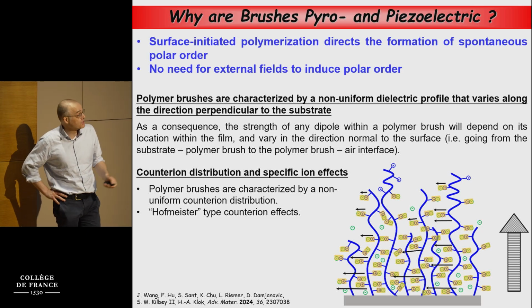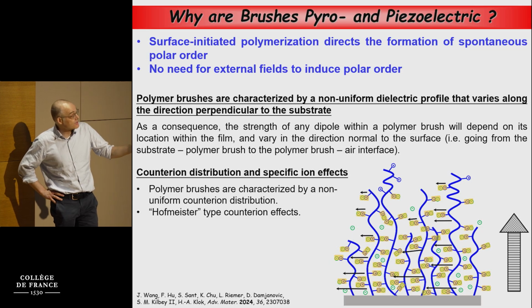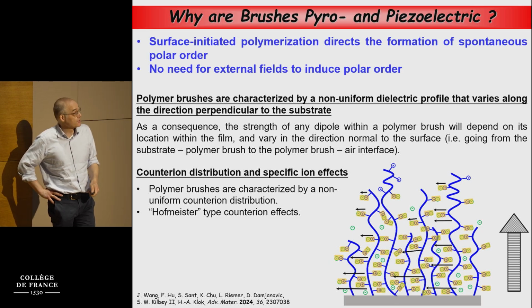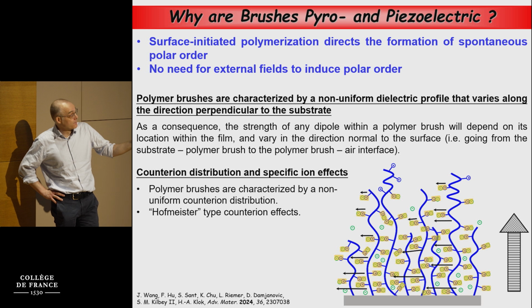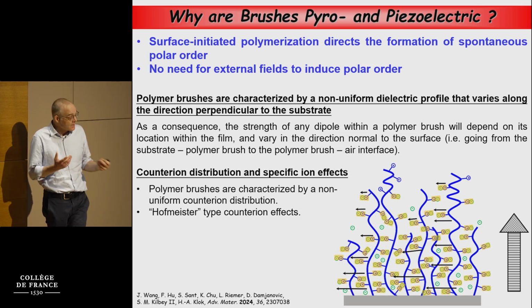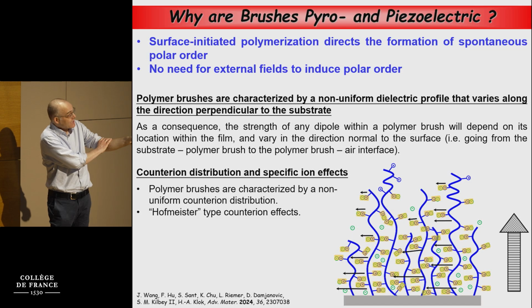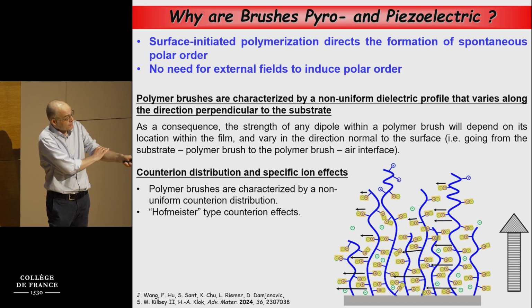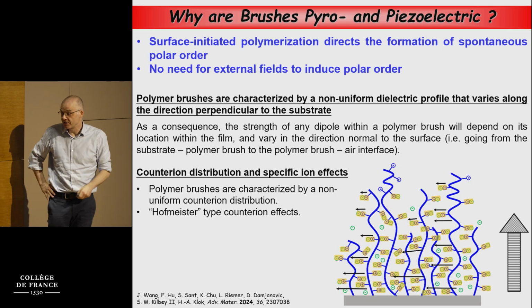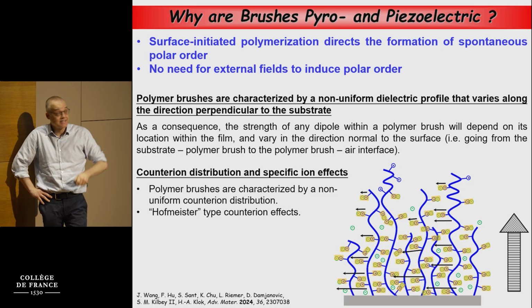That's a very complicated question, and so here are a number of arguments that we believe underlie these observations. The first point is that polymer brushes generally are characterized also by a non-uniform dielectric profile that varies along the direction perpendicular to the substrate, so in the z direction here. And the consequence of this, we think, is that the strength of any dipole within a polymer brush will depend on the location in the film. So the strength of a dipole close to the substrate, we believe, is different from the strength of a dipole somewhat closer to the air. And this already would induce some sort of directionality in the layer.